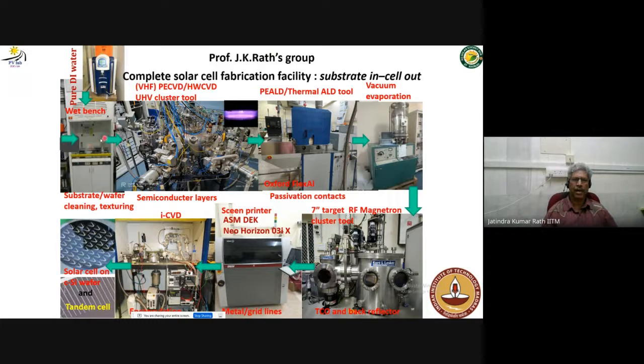You have a wafer which is cleaned here in a wet bench with DI water, high purity DI water, and a wet bench with RCA1, RCA2 cleaning. And the wafer goes to this PECVD chamber to make all the layers. Then it goes to ALD, that's atomic layer deposition, to make some of the layers again. Then it goes through some metal evaporation for some of the layers. Then it goes to a magnetron sputtering system to make some transparent conducting layers. And then it goes to metal printing.